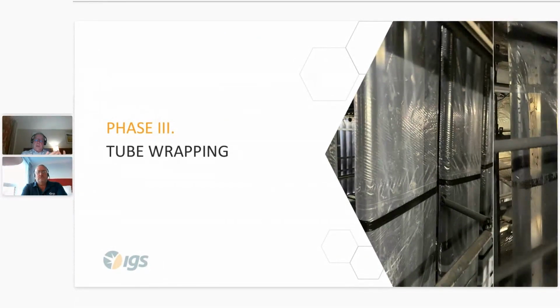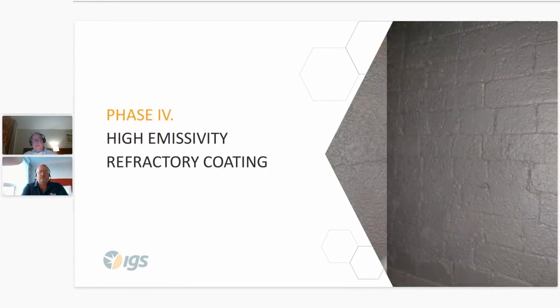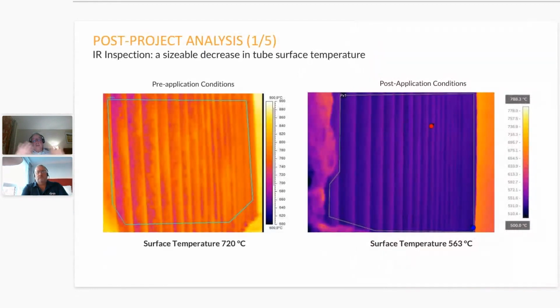We're going to wrap those tubes up and protect them because step 2 of the coating is to spray the refractory surface. Remember, we've got both surfaces we're working with to improve the radiant efficiency. So wrap the tubes. Now we're going to spray refractory. We have different formulas because we have different adhesion expectations, different thermal coefficients we've got to deal with. So we maintain adhesion during expansion. So we've got coating for fiber refractory blankets and for brick, insulating fire brick, castable, etc. Different formulas, different performance advantages.